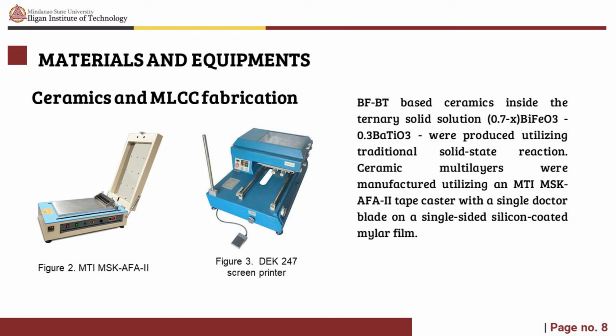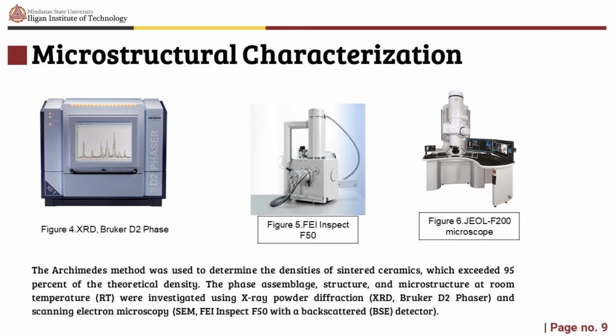Multilayers were sintered at 890 degrees Celsius for 2 hours, with an intermediate binder burnout step at 180 degrees Celsius for 4 hours and 300 degrees Celsius for 2 hours. The multilayers were coated with silver terminal electrodes and burned for 2 hours at 850 degrees Celsius.